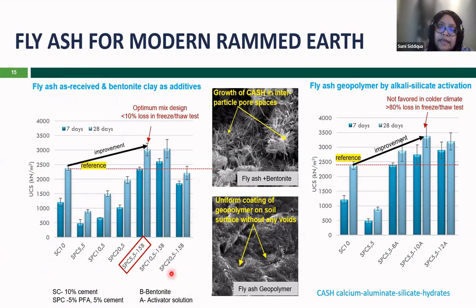So as you can see on our x-axis, we have several combinations of the materials. I'll explain what those materials are. The first one here is SC, which is 10% Portland cement. Then S refers to the raw sand material that we use for building those rammed earth. Then we have SPC 5-5, that means 5% fly ash from our project and 5% cement. Then SPC 10-5, that means 10% fly ash and 5% cement. Then we have 20% fly ash and 5% cement.